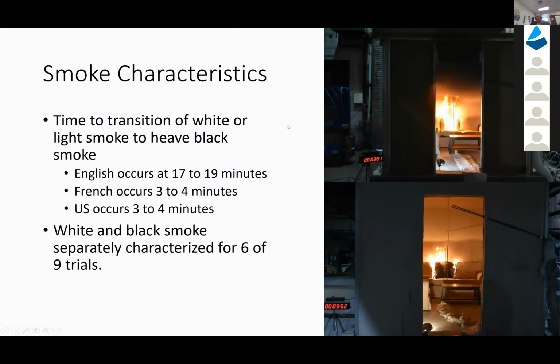So smoke characteristics. You can see that we have white smoke and black smoke that are developed as the burn progresses. The white smoke has a very different chemical composition than the black smoke. The black smoke has a lot more PICs, and as a result is a lot more toxic. And you can see that transition occurred in the previous slide at 17 to 19 minutes for the English furniture, whereas the French and US, it was 3 to 4 minutes into the burn.